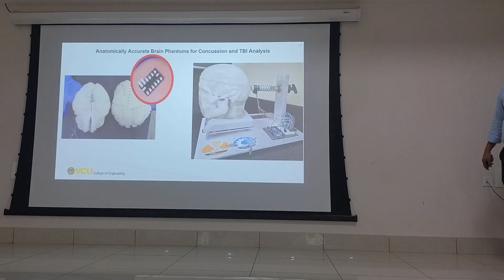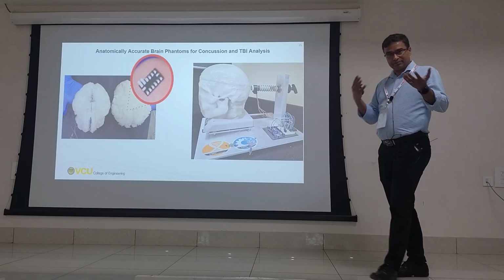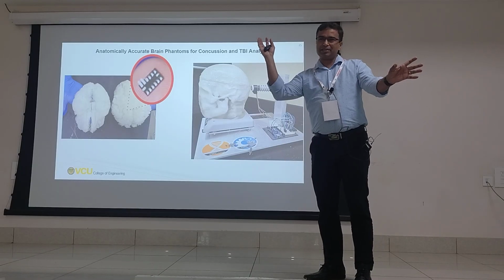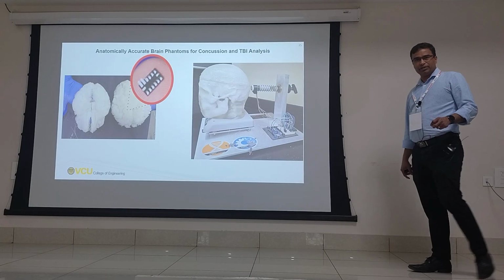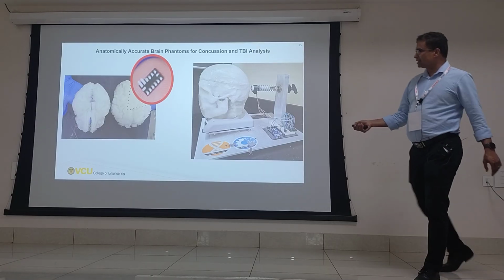Okay, this is what we did. We got an elastic constant here. If you take the modulus of G prime and G double prime, you should get the elastic constant K. K is basically the square root of G prime squared plus G double prime squared. Okay? Our K did not match the K calculated from this. That was because we went from a small sample like this to a big sample like this. So we revised that. Now we have a matching measurement, so our MRE measurements match the rheometer measurements. Okay, so now this is a viscoelastic brain hydrogel.